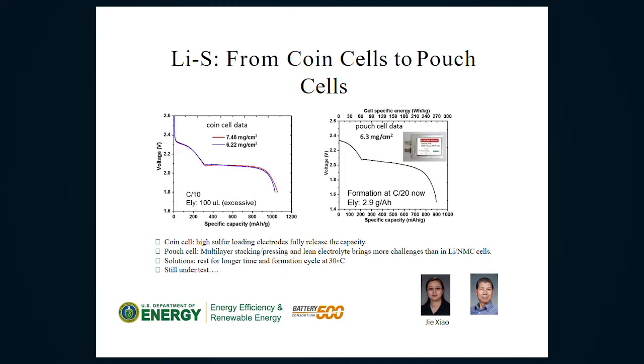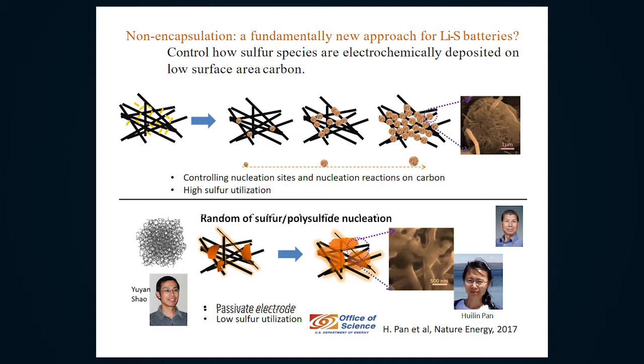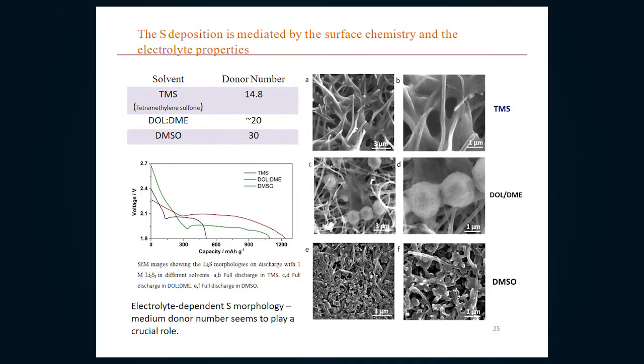But if you really do it under high sulfur loading controlled conditions, you cannot get the full capacity of the sulfur anymore. So finding new ways to do lithium sulfur that don't rely on high surface area carbon encapsulation is very, very important. We have been spending a lot of time on this. In this case, I'm showing you just one example where we don't use high surface area carbon. This is carbon fiber. It's very low surface area, less than 10. It has reasonable capacity, but the trick is you need to create a condition to make sure the reaction all happens on the electrode material rather than precipitating everywhere in the system.